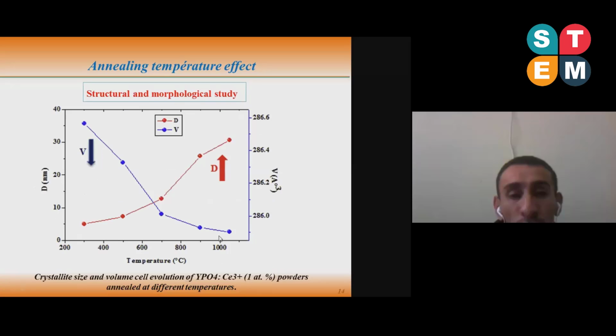The average crystalline size increases with annealing temperature from around 5 nanometers up to 30 nanometers for the sample annealed at 300 and the sample annealed at 1050 degrees Celsius, respectively. Also, at the same time, the cell volume decreases with temperature. The decrease in cell volume and the increase in crystalline size are related to improvement of the crystallinity and the decrease of the density of defects.